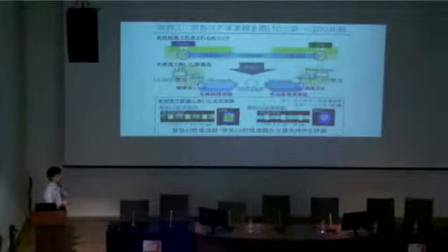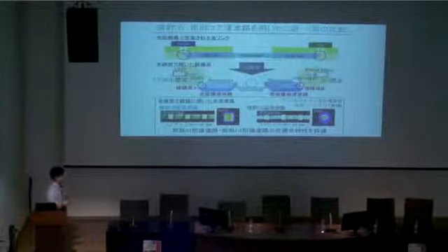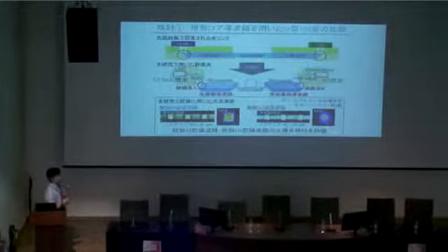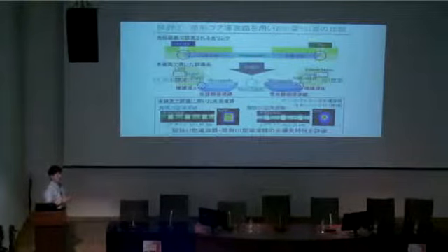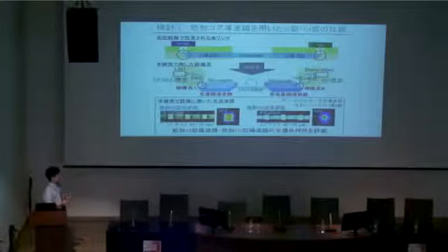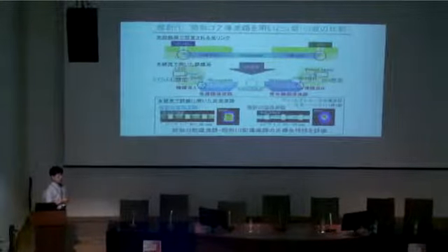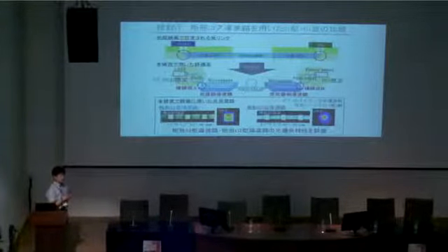Here, this is the step index core near field pattern. This is independent of the launching condition in general. So even if we use a single mode fiber with a small launching beam pattern, the whole core shows a bright output near field pattern. While in the case of graded index core, the light is tightly concentrated at the core center. That is the reason why we can obtain a good misalignment tolerance.